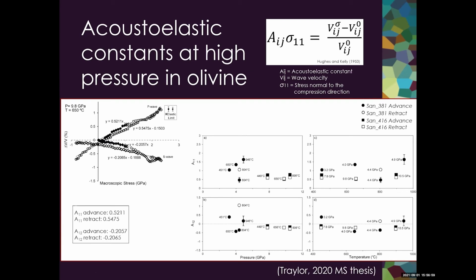And we can see that the acoustoelastic slopes during the advancement to the elastic limit, which is shown as the black data points, follow a similar slope to the retraction data in both the P wave and the S wave data. And we're seeing about a 0.5% wave velocity change per GPa stress for the P wave velocity data, and about a 0.2% wave velocity change per GPa stress for the S wave data.